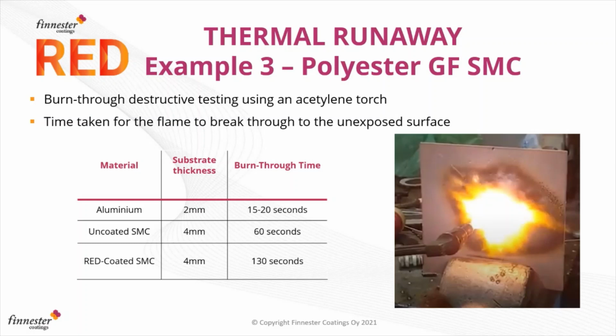And as you can see, our red coated SMC in this case actually doubled the period of time needed for that acetylene torch to get through and burn through that polyester glass fiber material. So very good, convincing evidence that our technology is contributing substantially to protecting these materials.